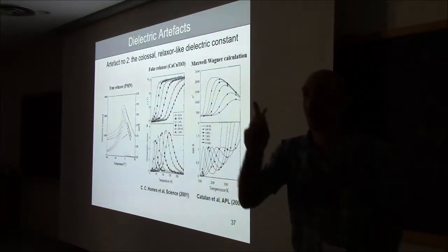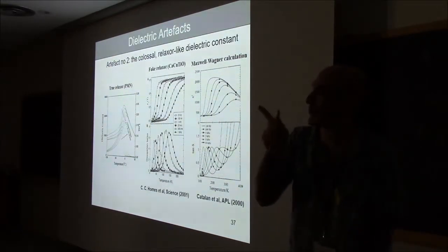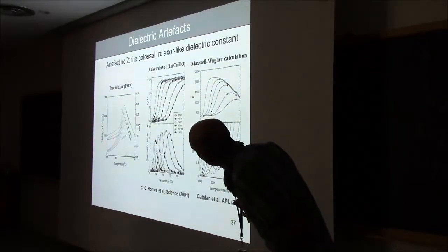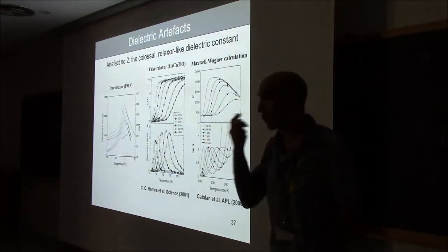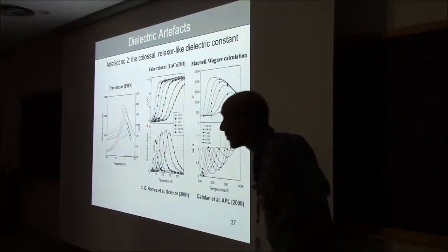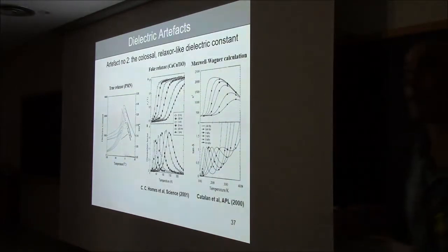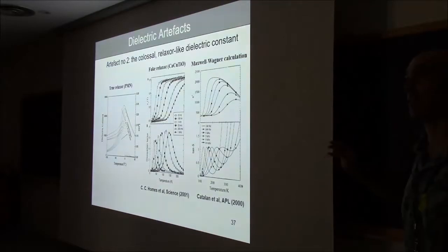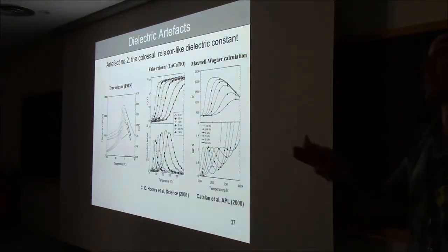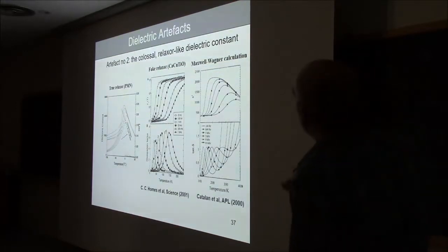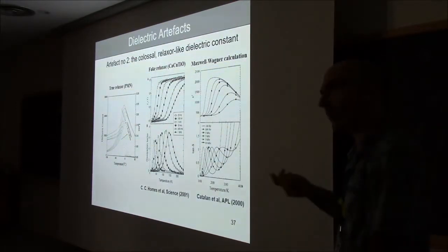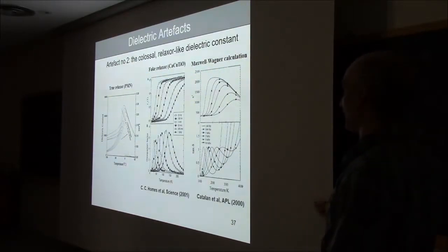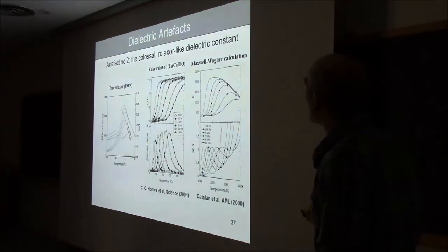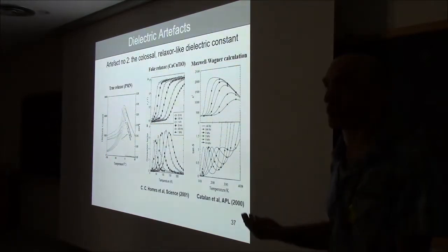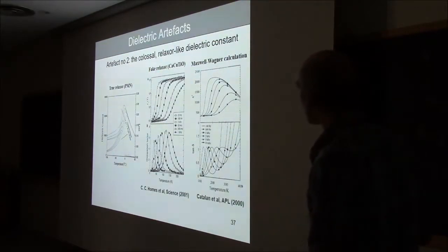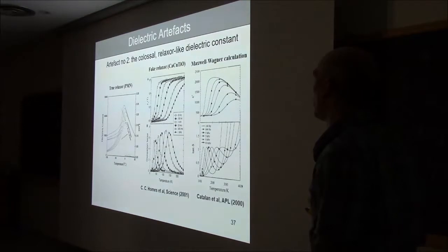Another important feature, and this is the one that you will use to distinguish between a true relaxor and a fake relaxor, is the frequency dependence of the dielectric loss. Okay? In true relaxors, the dielectric loss goes up as you increase frequency. That's quite unusual. For the artifact that I'm going to describe now, the opposite is true. The losses go up as frequency goes down. Okay, so classic example. This is calcium copper titanate. This became a very hot topic a few years ago. Not such a few years ago, two decades ago. People were measuring dielectric constants of the order of hundreds of thousands. You would think good for making capacitors, right? And they said that this was a type of relaxor. In fact, it's not. Okay?